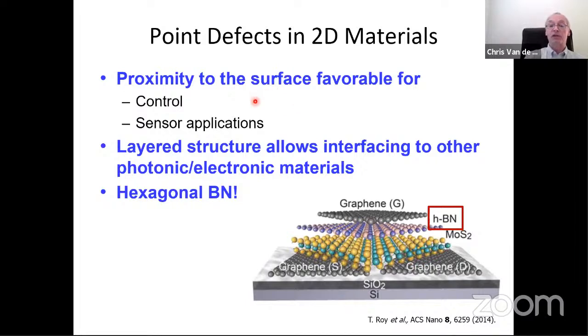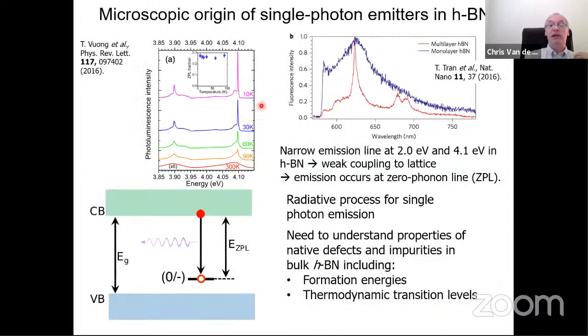And because the surfaces of these 2D materials are relatively inert, having a defect close to the surface is actually much more acceptable than it is in the case of diamond, for instance, where the surface can actually serve as a source of decoherence. So in this context, hexagonal boron nitride has turned out to be a very attractive material. Already a few years ago, it was demonstrated that very bright light emitters occur in hexagonal boron nitride that can emit photons in a controlled manner in the form of single photons, which would be very attractive for quantum applications. Okay.